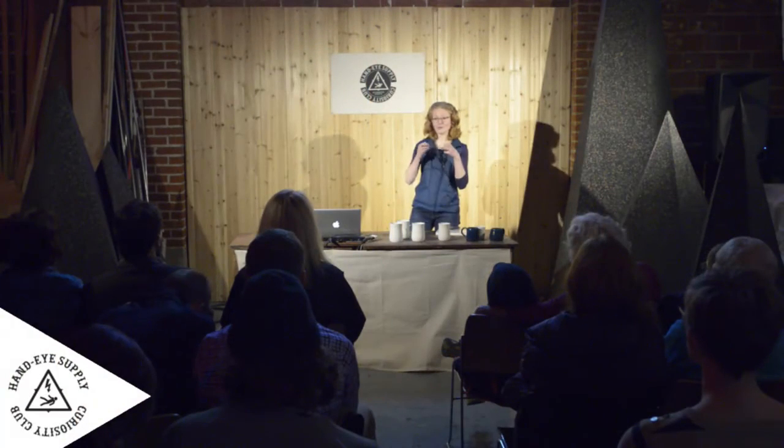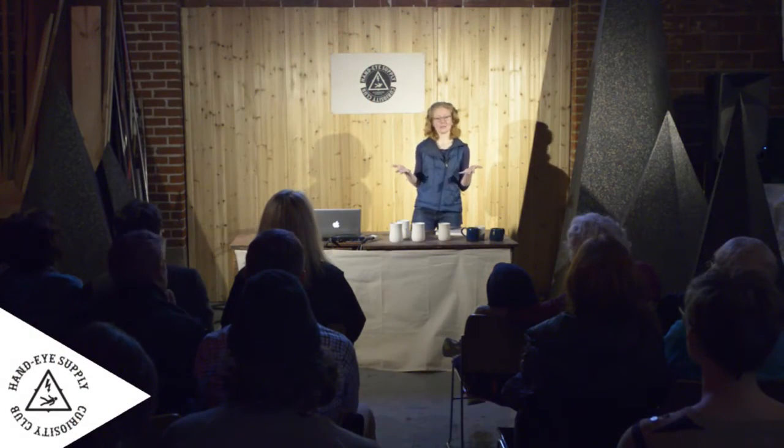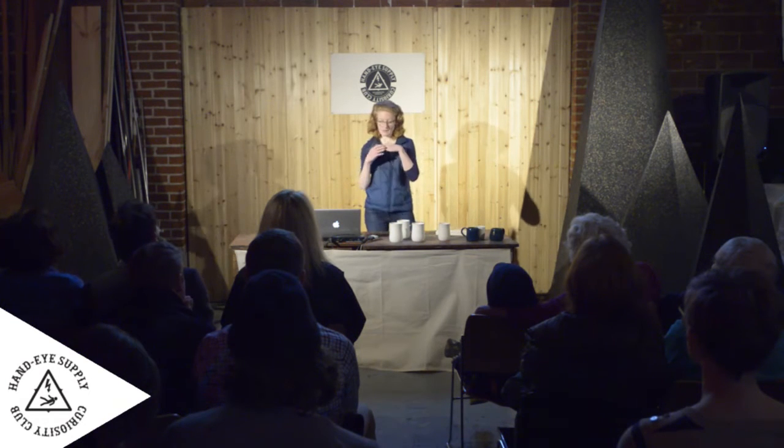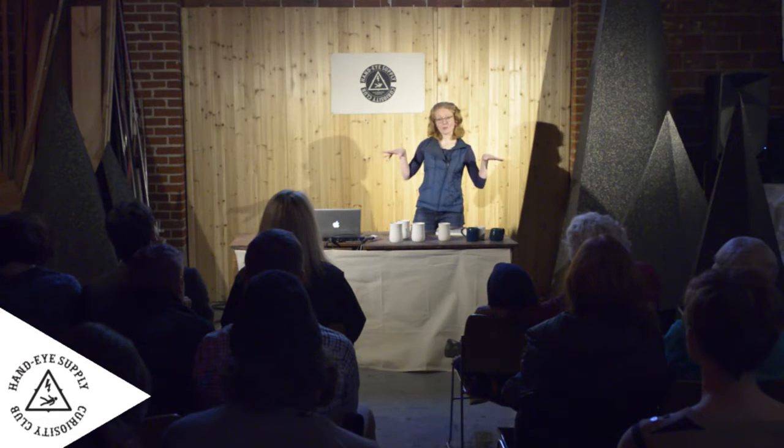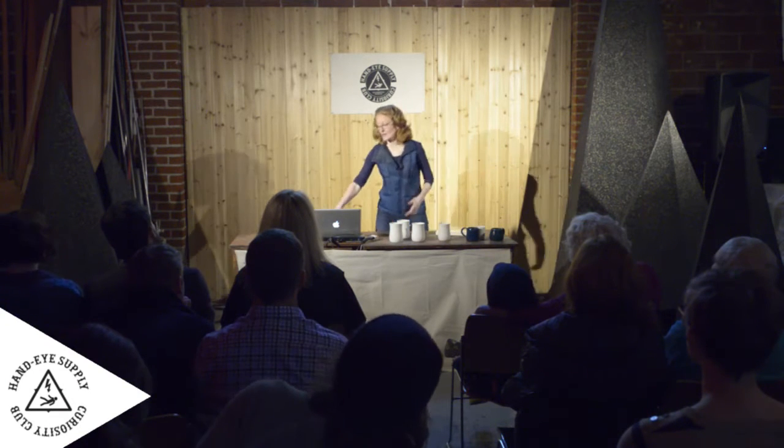So you start out, you stick the dry greenware into the kiln. And the first thing you do is to just slowly raise the temperature to just below the boiling point of water. And that's because if you have any water still in there and there's enough of it all together, the water's going to boil and that can break apart your piece. But you can avoid that by letting it sit below the boiling temperature, drive all that water off first, and then you're good to go.